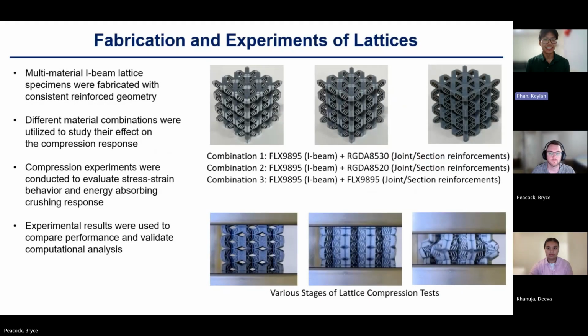Fabrication and experiments of lattices. Multi-material I-beam lattice specimens were fabricated with consistent reinforced geometries. Different material combinations were utilized to study their effect on the compression response. Compression experiments were conducted to evaluate stress-strain behavior and energy-absorbing crushing response. Experimental results were used to compare performance and validate computational analysis.